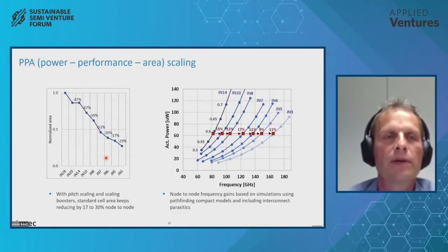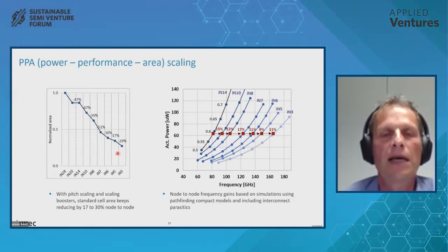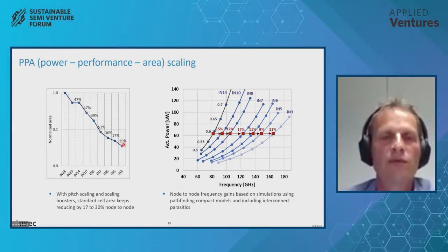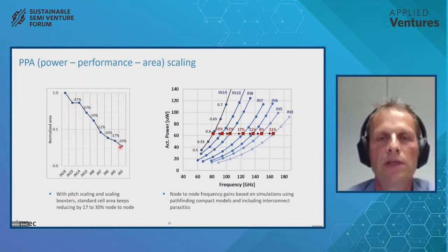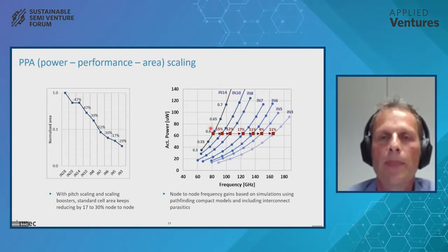Okay, so let's first look at the classic one, power performance area scaling. So going from a 28 nanometer node now down to 3 nanometer, we see that there is progressive area scaling. We are improving node to node on the area scaling. So by using these advanced concepts of making FinFETs and then nanosheets, etc., we can continue the area scaling. And furthermore, the performance is also improving. So if we look at the active power versus the frequency, we see that the frequency is improving node to node. If we look at a constant active power, or equivalently at a given frequency, we see that the active power is reduced from node to node.